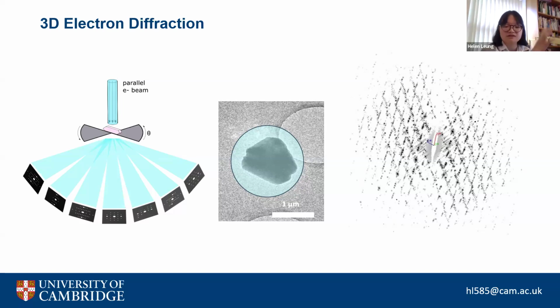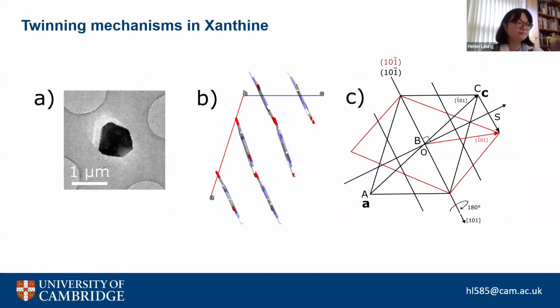Looking at the structure of xanthine, you could imagine we've got very tightly hydrogen bonded layers, held together by relatively weaker van der Waals forces. So you could imagine there is some flexibility in the structure around the positions of these layers with respect to each other. So the first thing we did with the 3D ED data is calculate the orientation matrices of the 2 reciprocal lattices that we do see and relate them to each other.